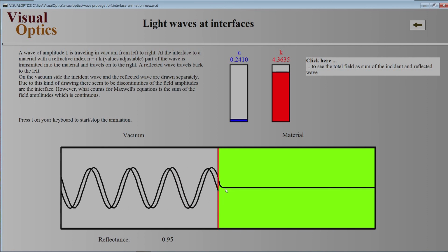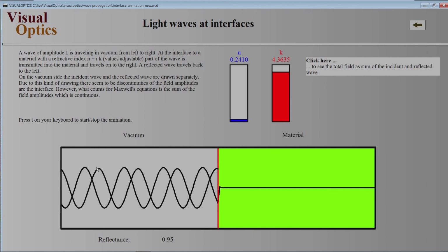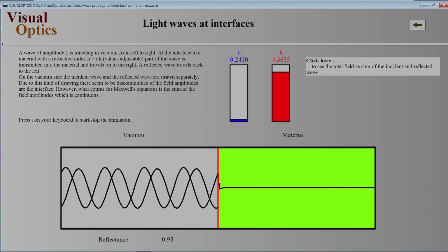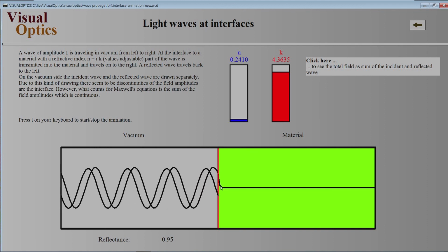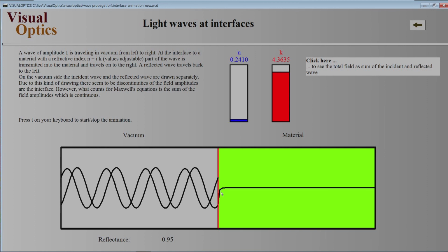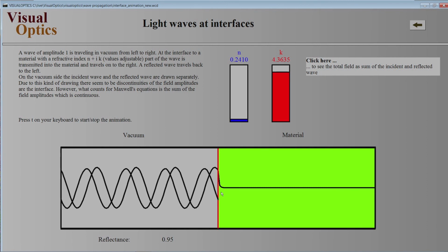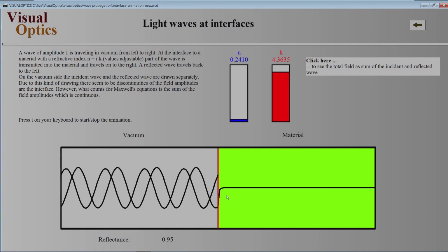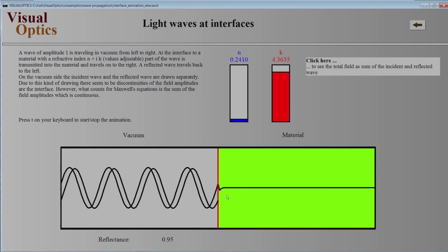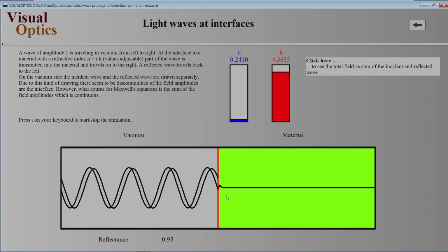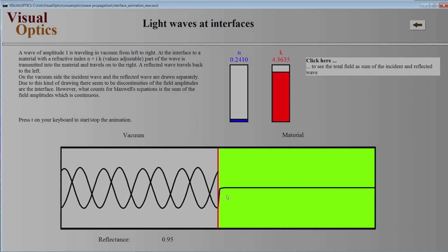This is called the skin effect, and this absorption can be pretty dramatic if you use this material as a mirror, and if you have a strong light source like a high power laser, then maybe 5% of absorption in a very shallow layer of a few nanometers only can lead to a melting of the mirror and a real damage. So that already tells us now metallic mirrors are not really a very useful tool for high power laser mirrors. There we need something different. We will discuss that later on.